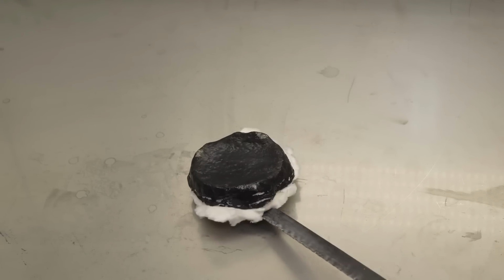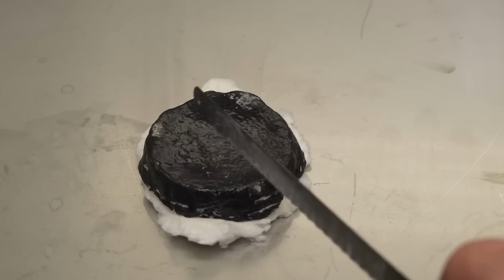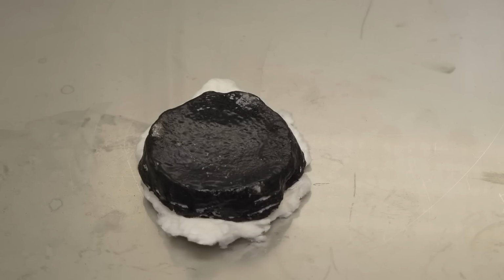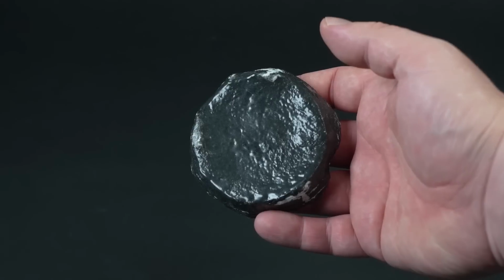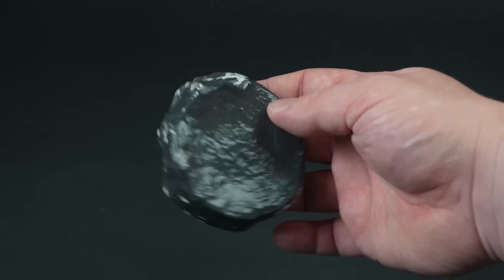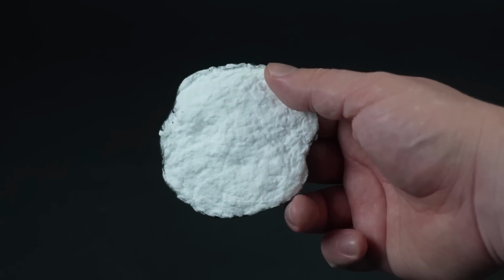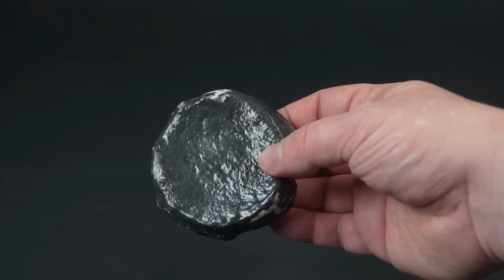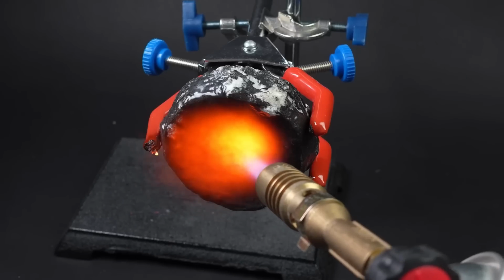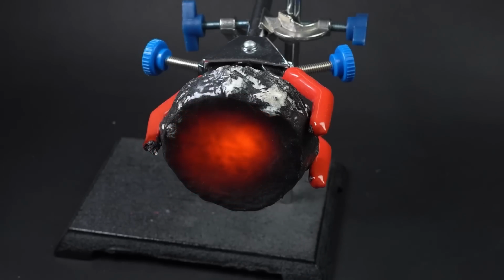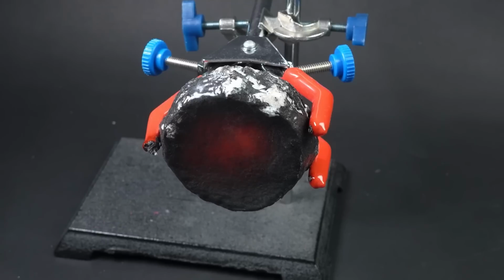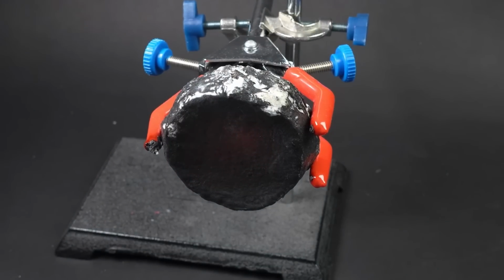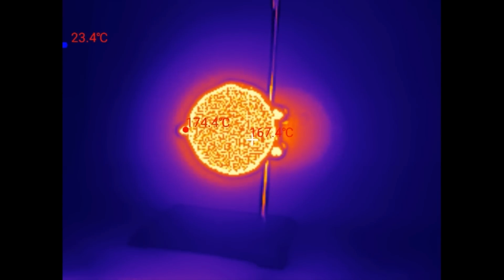After cooling, my painted thermal protection tile can be examined up close. As can be seen, at least on one side, the coating turned out to be quite even. Although after sintering, such a tile has shrunk a bit. Apparently, part of the quartz fiber fused with the black coating. It is interesting to see how quickly it will cool down when heated with a gas torch. Yes, as can be seen, this happens quite quickly, as evidenced by the readings of the thermal camera, especially when viewed from the backside of the tile.